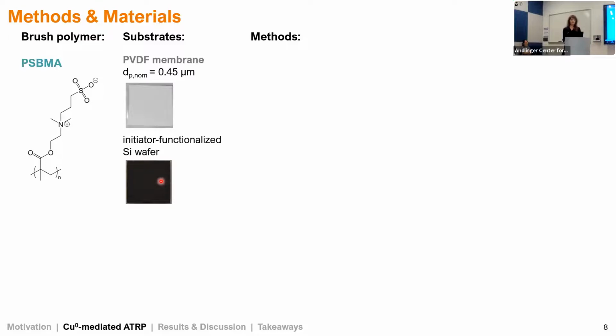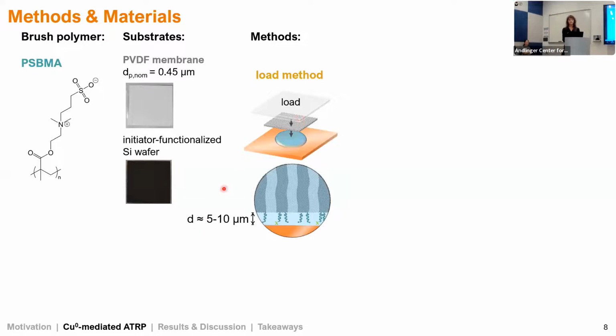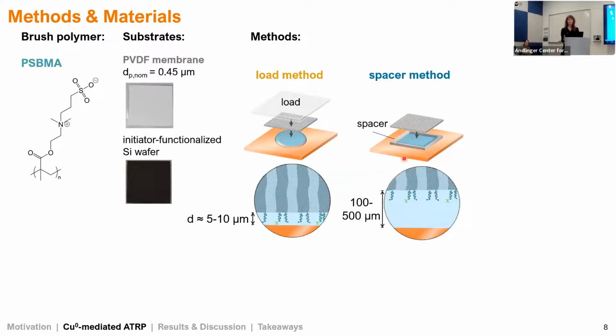And in terms of methods, we looked at 3 different methods that have been used in the literature. The first I'm going to call the load method, just for short. In this scenario, we place a load or a weight on top of our substrate to bring it into contact with reaction solution. And this gives us a very small distance D on the order of 5 to 10 microns. The second is what I'm going to call the spacer method. In this case, we're just using some spacer material to maintain a wider distance D between our substrate and copper plate. This is typically 100 to 500 microns.